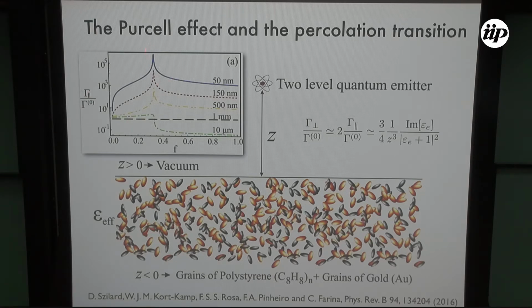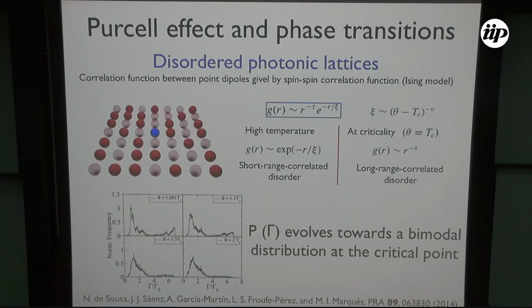So this is a nice result showing that indeed you can not only be close to some non-trivial boundary condition, but it shows that a phase transition can cause enhancement of the spontaneous emission rate. In that example, the emitter was outside the material going through the phase transition.